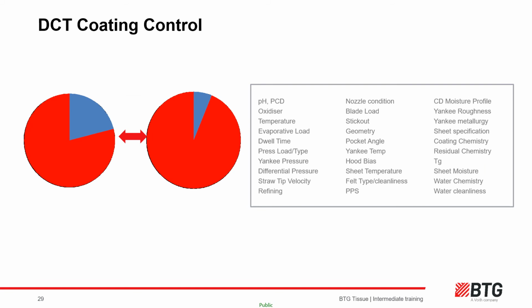So the coating makeup pie chart on the left is what we would normally see from an LDC machine. Using BTG's trash balance survey, we are able to semi-quantitatively calculate the percentage of coating contaminants to the overall combined coating add-on, and based on our collective monitoring around Europe, would recommend a Yankee coating contamination factor of less than 75% to be a safe figure when considering potential hard or unresponsive coating, which could lead to issues including chatter.